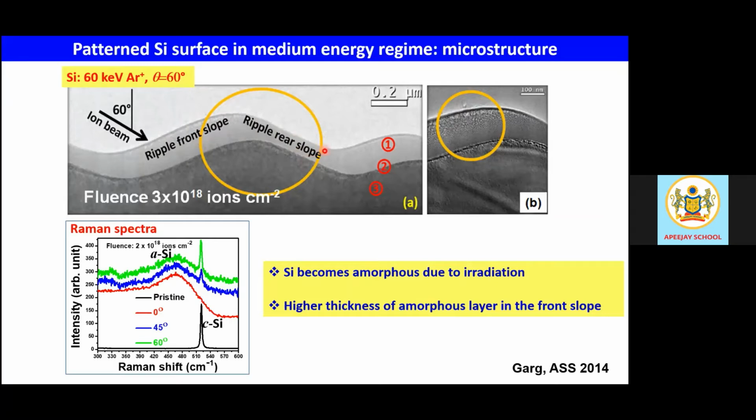So at the valley it is reduced compared to the hill. This is because, for the same energy and same material, the valley regions get eroded faster compared to the hilltops, that's why we see this non-uniformity in the ripple layer. But nothing surprising, this can be explained as I told you.